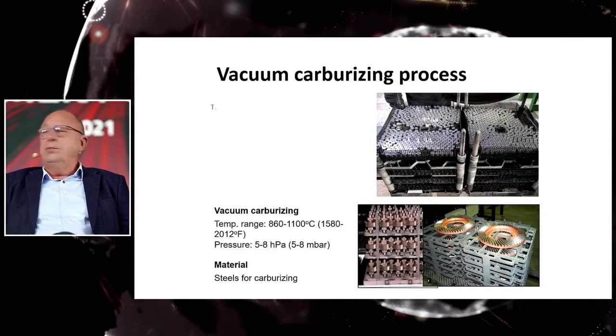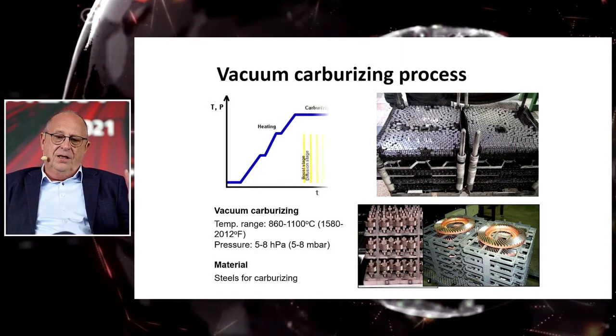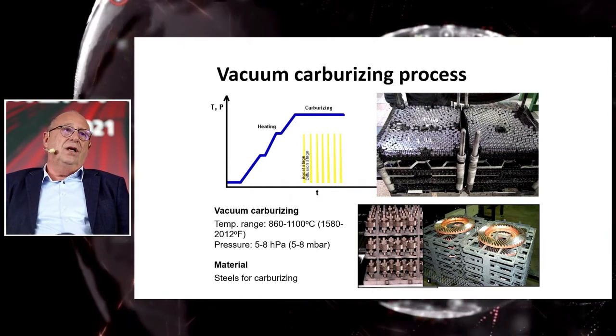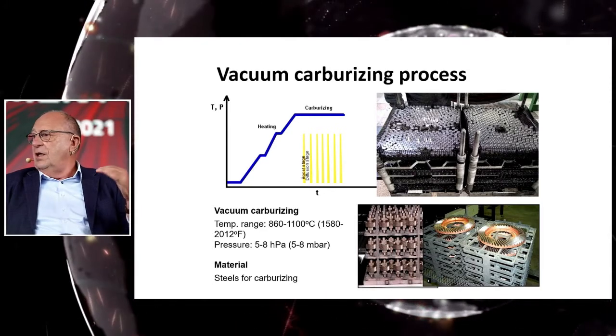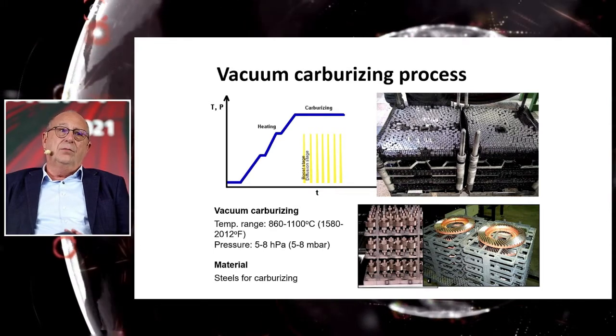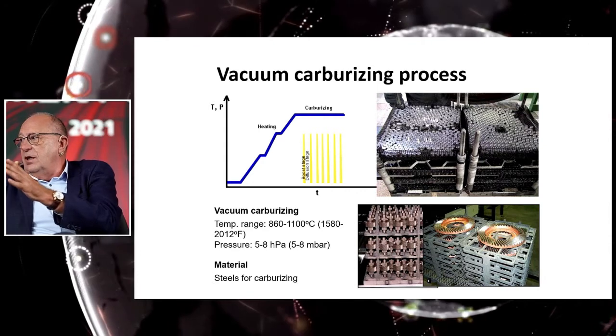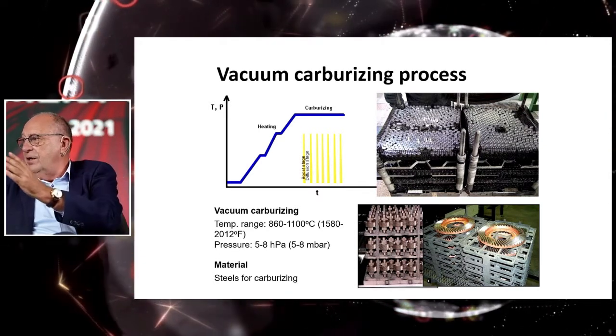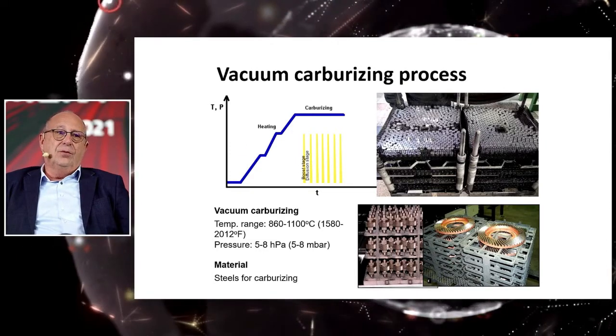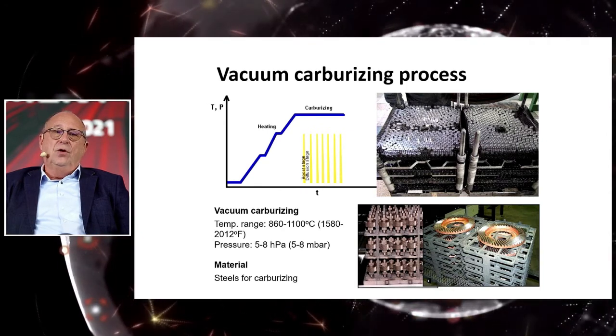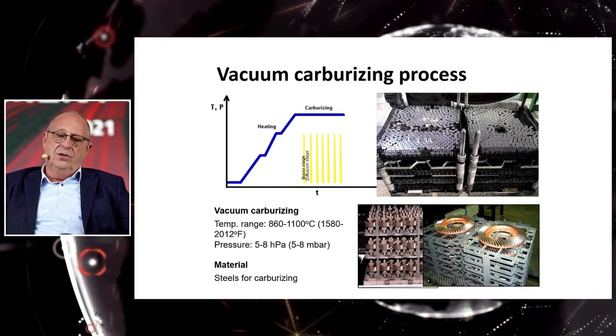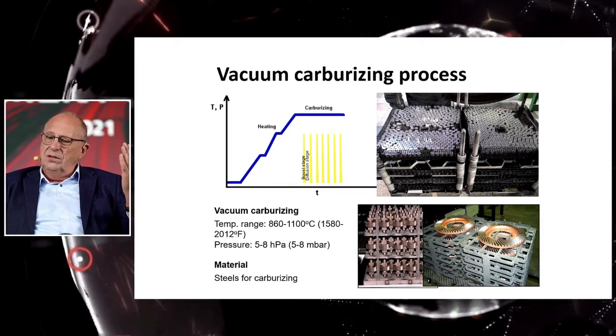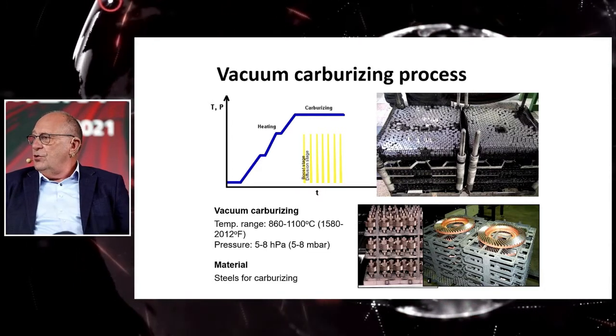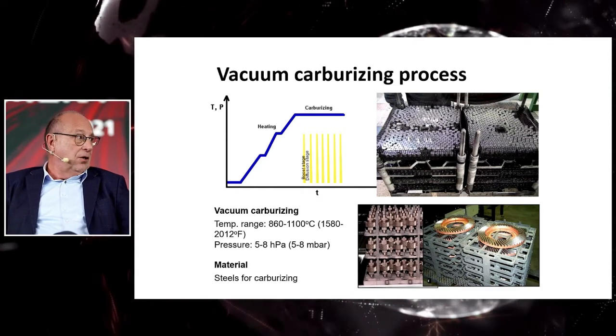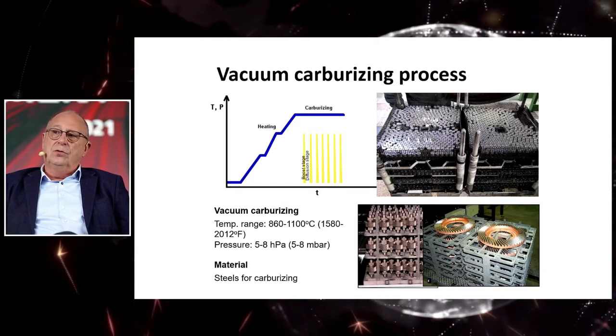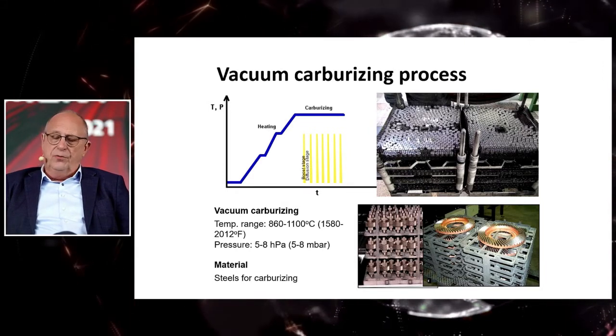A few words more about vacuum carburizing to make the process more understandable. The heating to the high temperature goes in an inert atmosphere at vacuum, and the carburizing period is divided into several segments: boost and diffusion, rich in carbon, poor or zero carbon. Consequently, the development of the carbon profile goes at non-steady state boundary conditions on the surface, and it is a difficult issue to be solved using traditional methods. Therefore, we built a special algorithm to plan and simulate the development of carbon profiles.